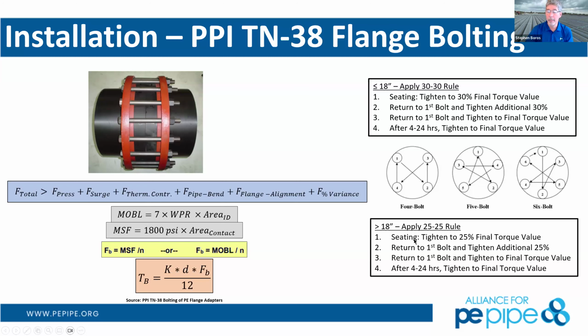If you're going to do greater than 18-inch pipe, you do the exact same thing, except you go through one more step and you only start with 25% of the torque value, additional 25, additional 25, and then the final value after, again, that 4 to 24 hour period to allow it to relax and creep a little bit, if you will, and make sure that you're going to have that final force where you have a flange that won't leak.